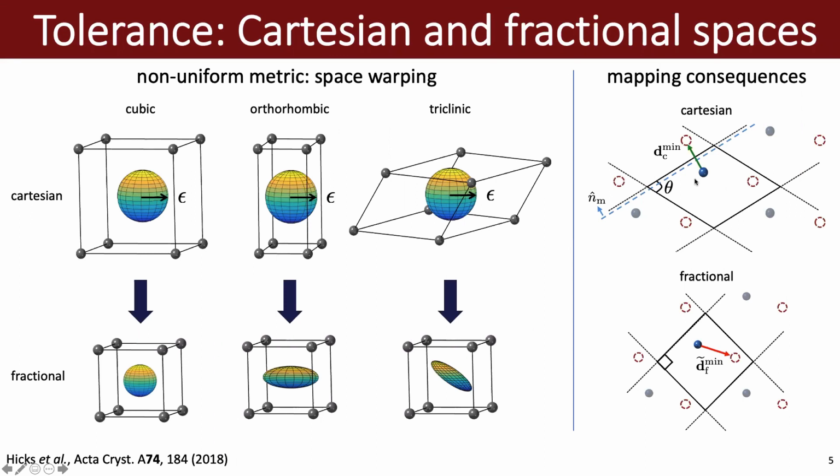To determine whether or not this is a mapping of the crystal, we need to perform a minimum distance calculation between the original blue atoms and the symmetry transformed orange atoms. We need to consider the method of images since we have a periodic crystal. And so we see that the minimum distance to this atom is this neighbor here, and we call this DC min.